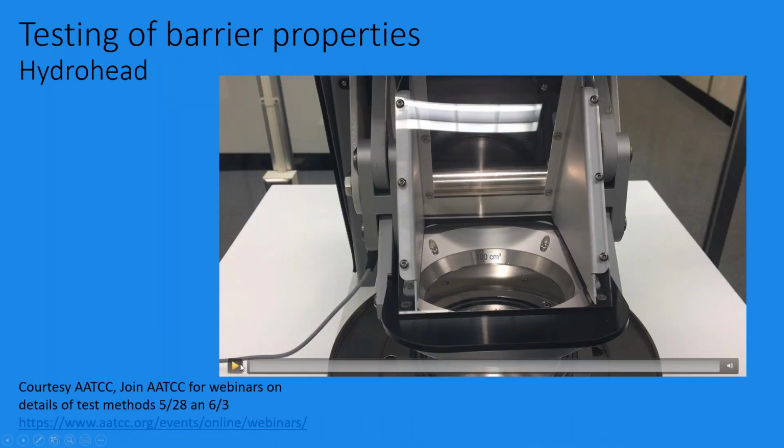I wanted to show you this video, and this is courtesy of our friends at AATCC. They're here in Raleigh, and soon they're going to do some webinars just on these test methods. These are just a few test methods that show how good the barrier actually is. And this is called a hydrohead. The reason I wanted to show you a hydrohead is the melt blown is so resistant to water, like I said, that you have to push the water through it. Its barrier properties are defined by how much pressure it takes. And so this is the standard test method to know what that barrier property is.